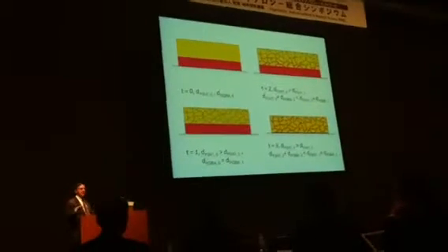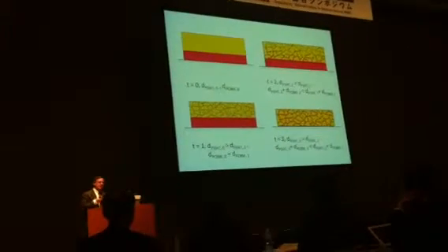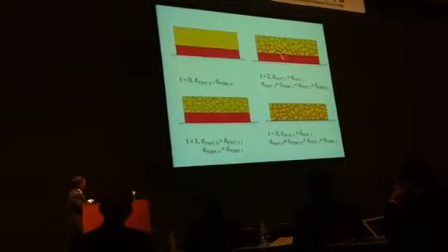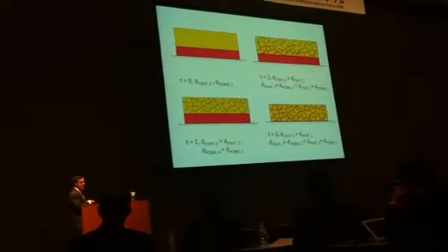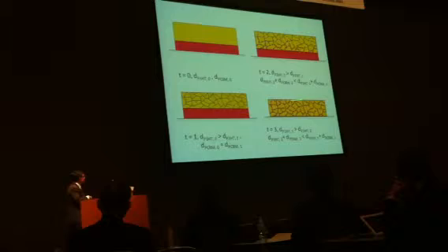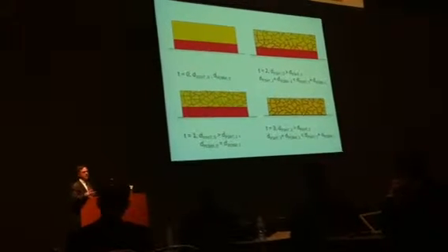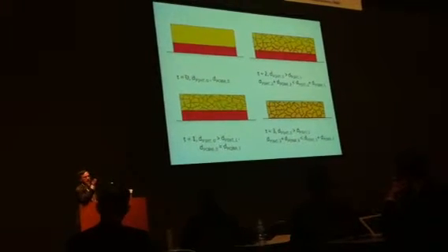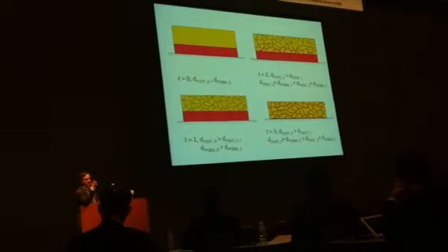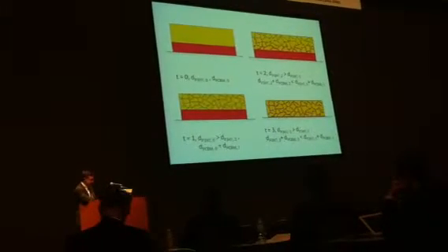Nonetheless, the model that we're developing is that the P3HT orders, and the PCBM is drawn through the areas that are between intercrystalline regions of the P3HT. We basically get a very rapid drawing of the PCBM through the P3HT layer, and you get a situation whereby you have crystals of P3HT. We have these intercrystalline domains which are effectively amorphous. We have a mixture of PCBM and the P3HT.